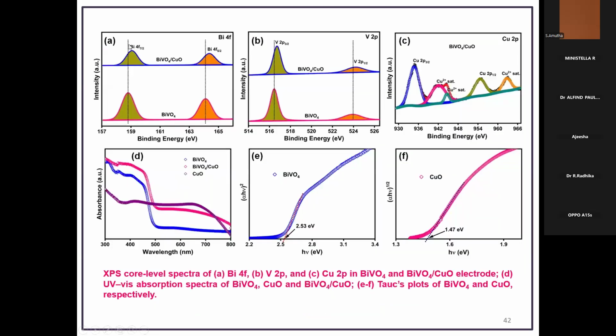This XPS analysis shows that before and after making the heterojunction, there is a shift in the binding energy for both the core levels. So that reveals the successful formation of a heterojunction between the two interfaces. Then after forming the heterojunction, the visible light absorption got enhanced. We have calculated the band gap using the Tauc plot method for bismuth vanadate and copper oxide, like 2.5 electron volt and 1.47 electron volt.